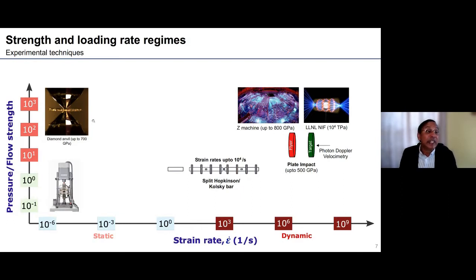This is a very elegant technique which can go to very high pressures, but under quasi-static conditions. When you go to high strain rates, then one goes to techniques such as plate impact. Obviously, many of us are working using the Kolsky bar or the split-Hopkinson bar. In this case, the pressure is nominally zero, because of the limited uniaxial stress condition, and of course it can go to high strain rates on the order of 10^4 per second.